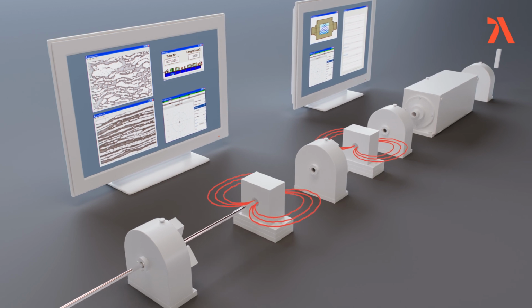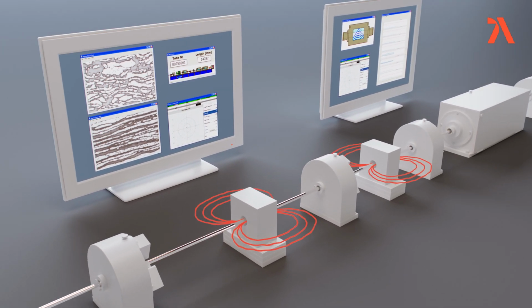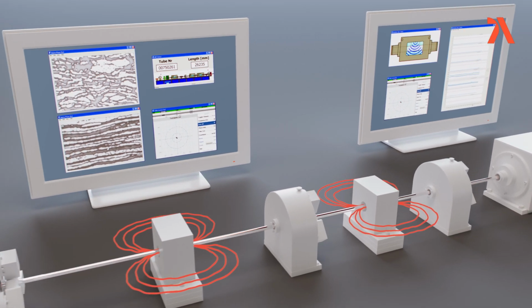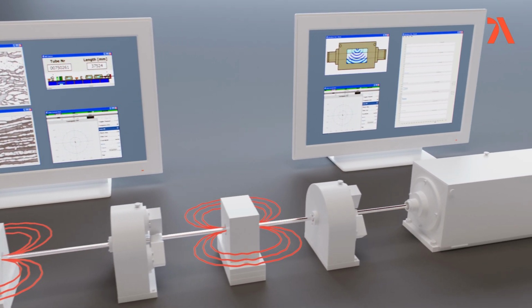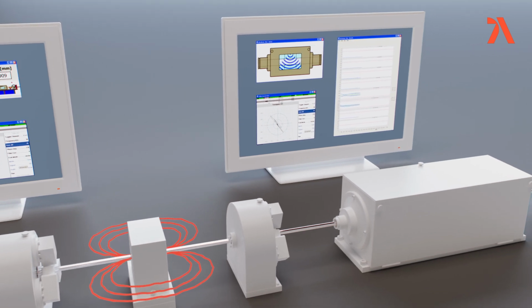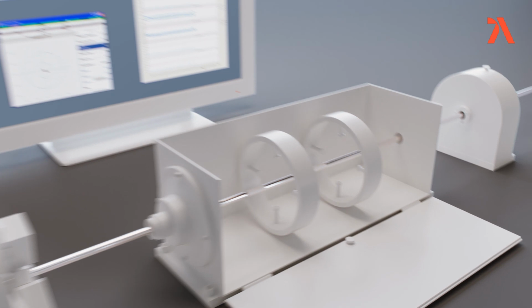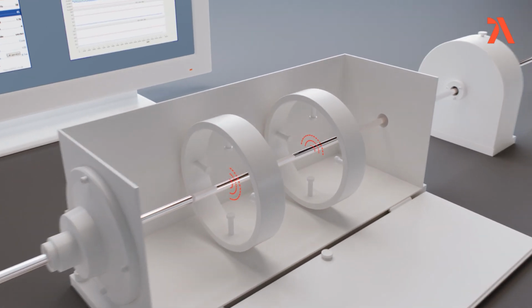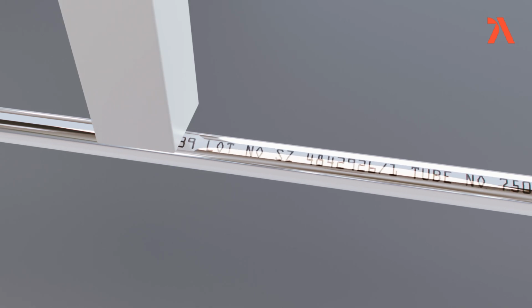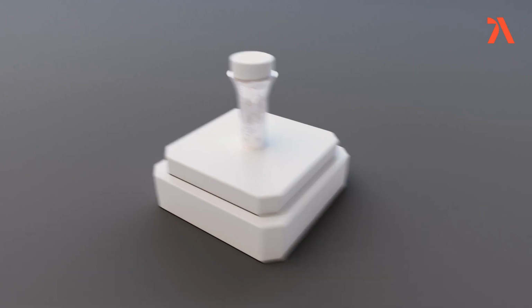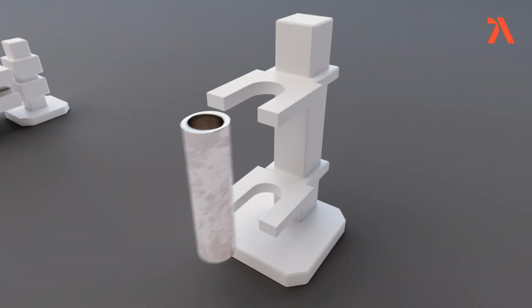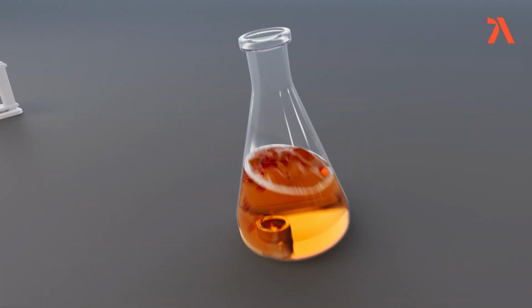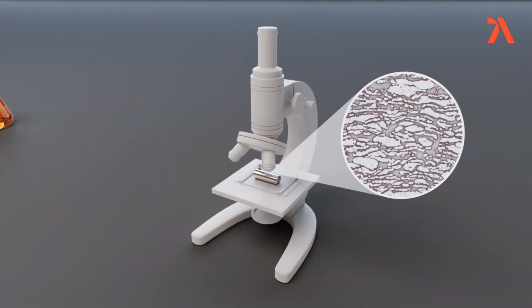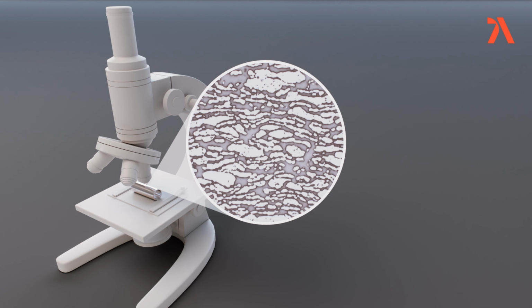every single tube is fully inspected for defects using ultrasonic and eddy current testing methods set to discover very small defects such as cracks, cavities, or other material defects that the naked eye can't detect. Tube dimension is verified as well as freedom from intermetallic phases. This is followed by visual inspection. The destructive testing stage includes flaring, flattening, and tensile strength tests. Corrosion and microstructure properties are also verified. Such tests are crucial to ensure the material meets customer specifications.